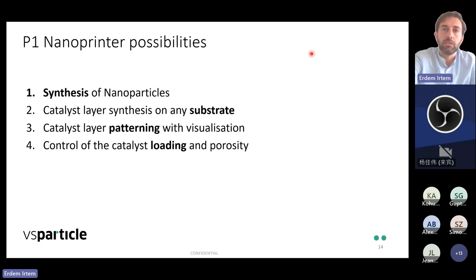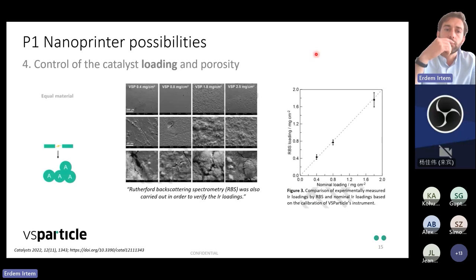What about the loading and the porosity? These are questions that we often face. You can control the loading. For example, from the same article, you can see that the iridium content was controlled by changing the deposition time. So instead of creating a deposit in an hour, you create it in 2 hours, 3 hours, 4 hours, or 10 minutes. So you are basically changing how many milligrams you have on the sample per hour. Then when we check this sample with Rutherford backscattering spectrometry, we find that the loading profile is quite uniform in different settings. This can be found in the same article with more information.